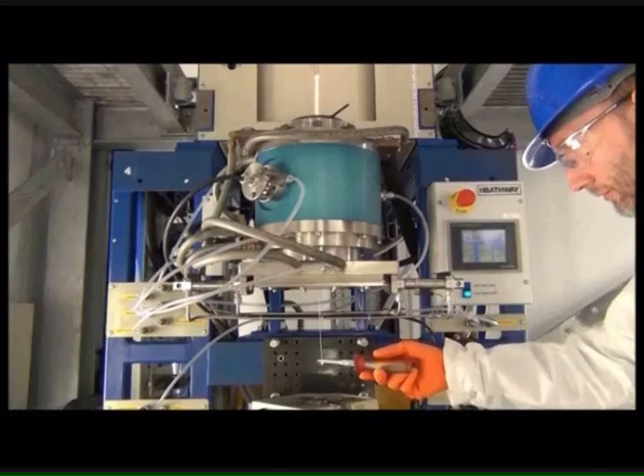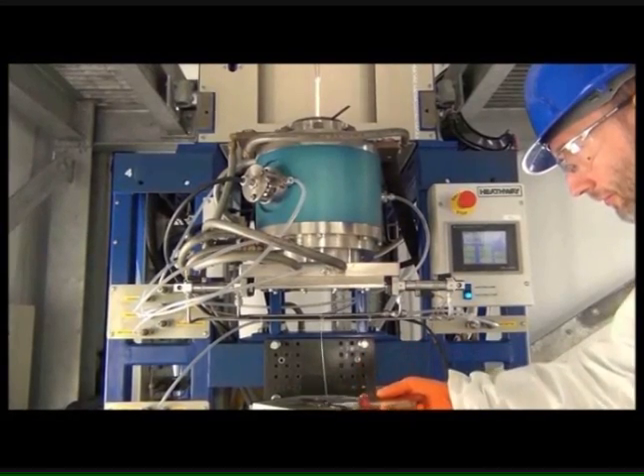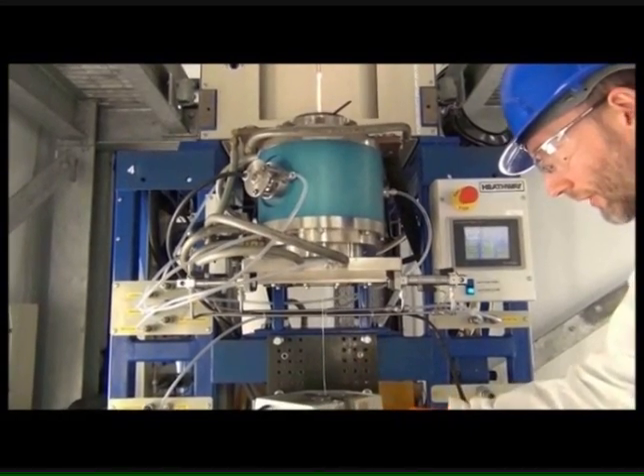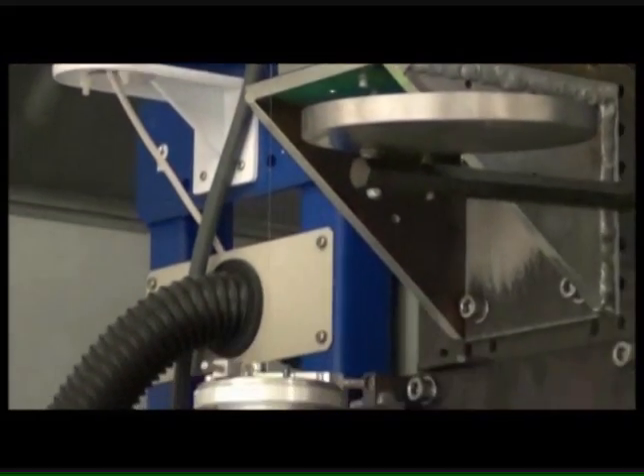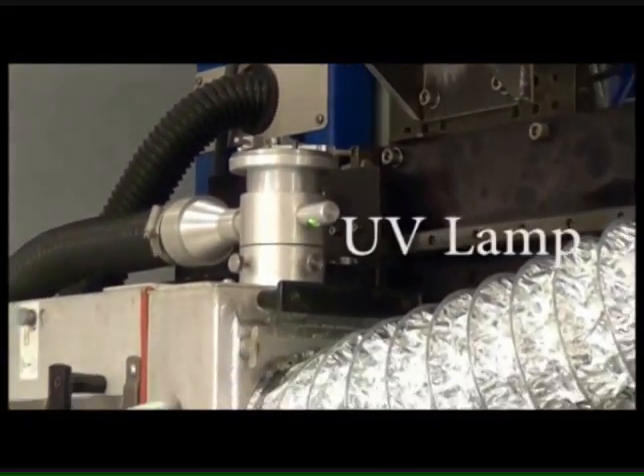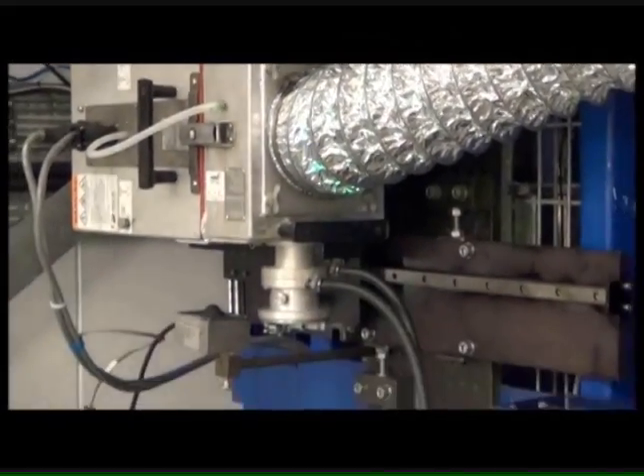The furnace heats the structure up to around 2000 degrees C at which point the glass becomes plastic and can be drawn down into the fibre structure. The fibre passes through a coating cup which applies a polymer coating to the outside of the fibre which is then cured with an ultraviolet lamp. This coating prevents any mechanical damage from occurring to the fibre.